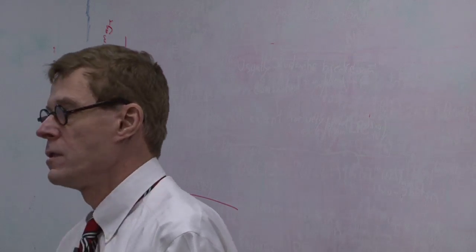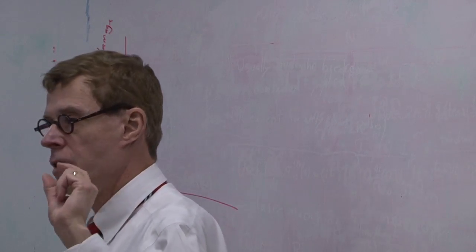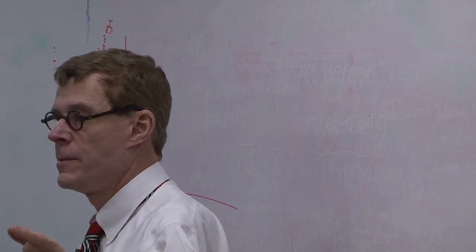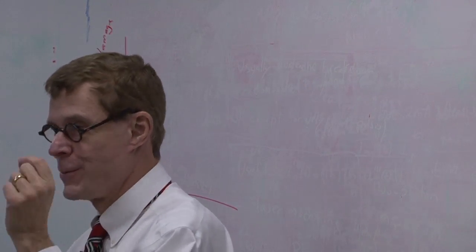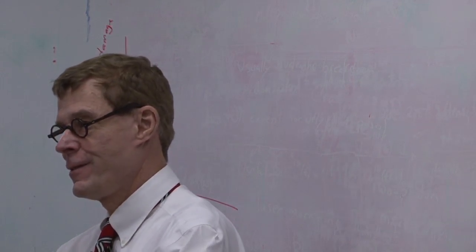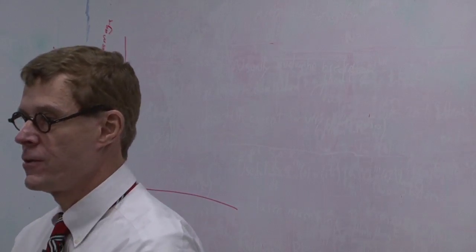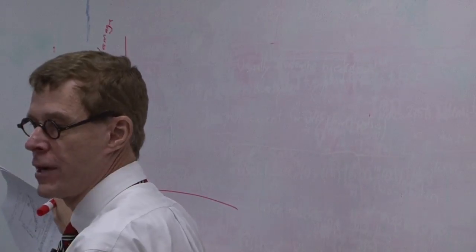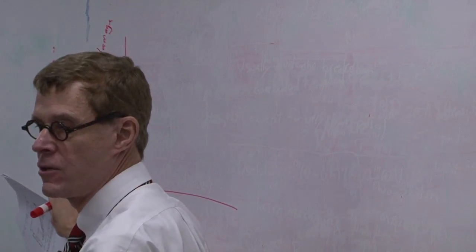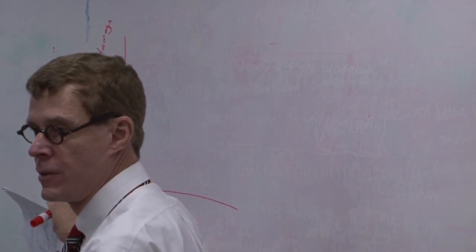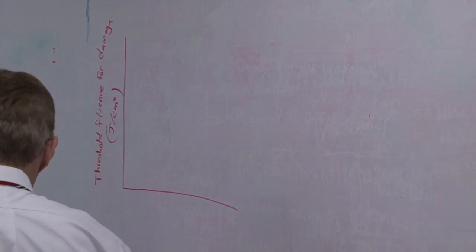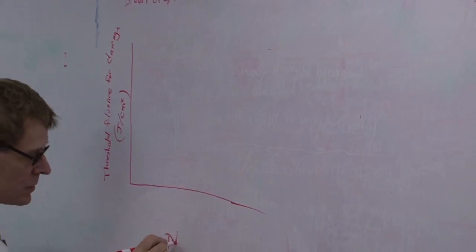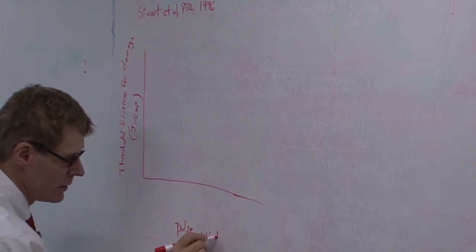If you're doing short pulse lasers, you often know how much energy you have, but you don't always know exactly how much intensity you have, because you have to make a very accurate determination of the time evolution of the pulse. So for practical reasons, you ask how much energy did I have to dump into the sample in order to damage it? And they did this as a function of pulse width,